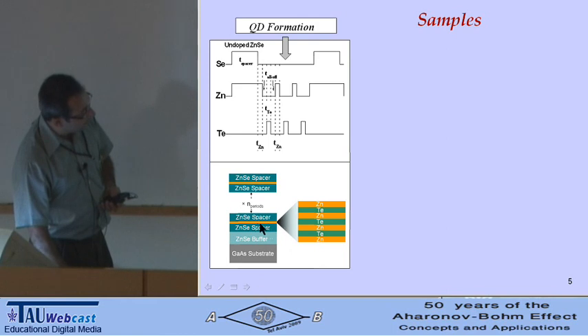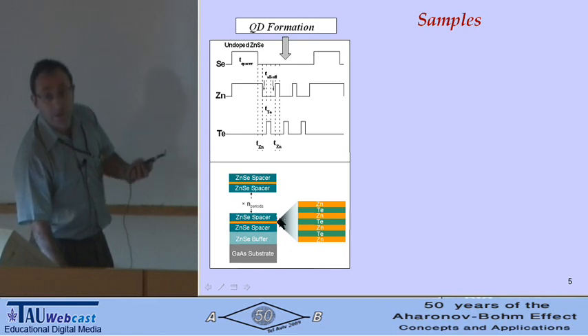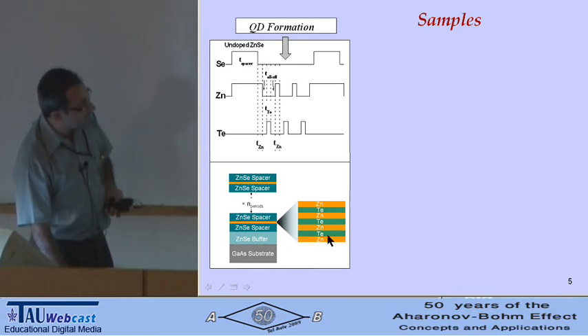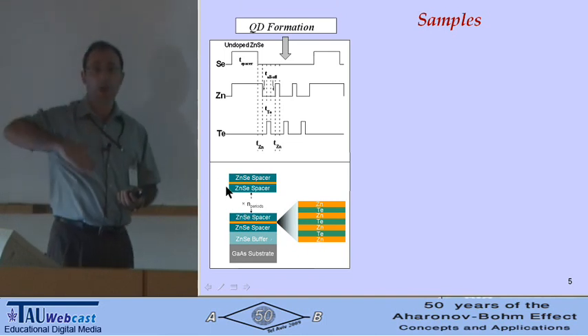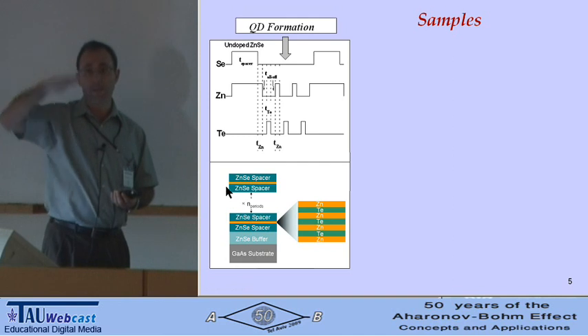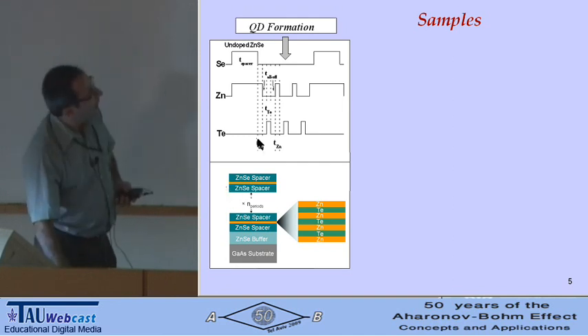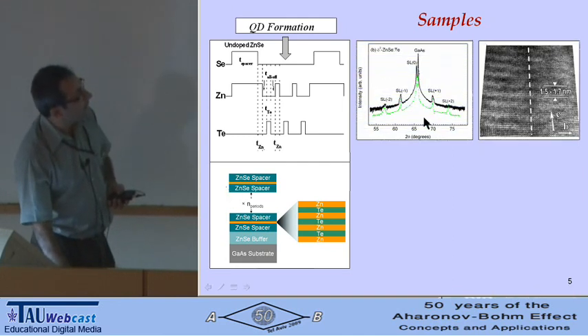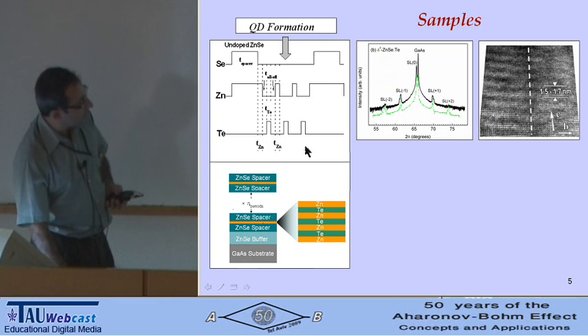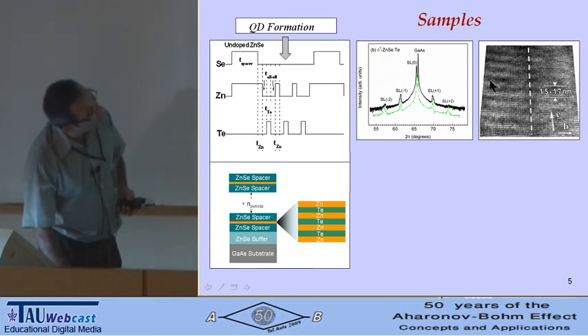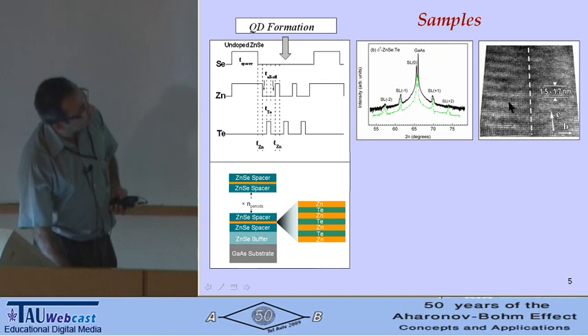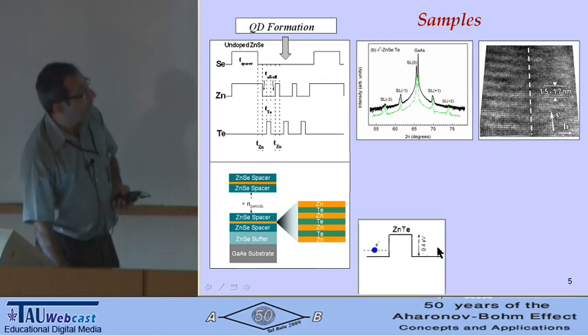You have each layer, which I will call the quantum dot containing layer, grown by this repetition. And these periods are repeated many, many times, about 200 times. So the dots get stacked. That's a high-resolution X-ray, so you can see the superlattice periodicity, which is the period of these stacked dots. And this is an electron microscopy image, so if you want to believe, these are our stacked quantum dots.